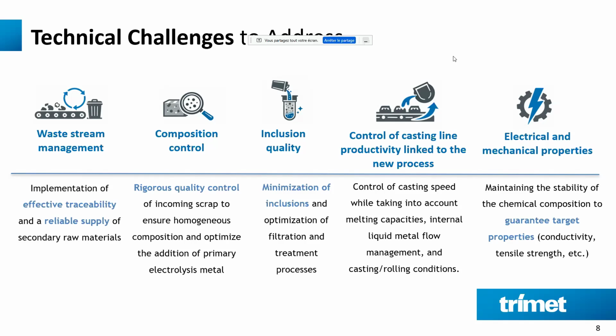Then obviously, when we receive the material, we have a check on composition, because depending on the quality of each delivery, we may or may not be able to use it. And even if we may be able to use it, the quality of the aluminium received, even from cable dismantling, can be very different. We could see from the small volumes that we receive from RTE, for instance, that from time to time we have different metal with not the same quality of, for instance, some side material like silicon, magnesium, and so on. And obviously, all this will have an impact at the end on the conductivity.